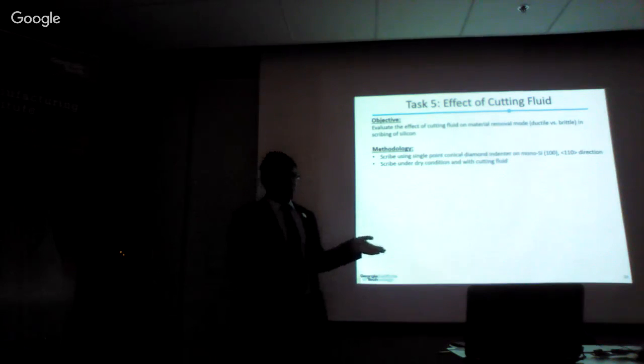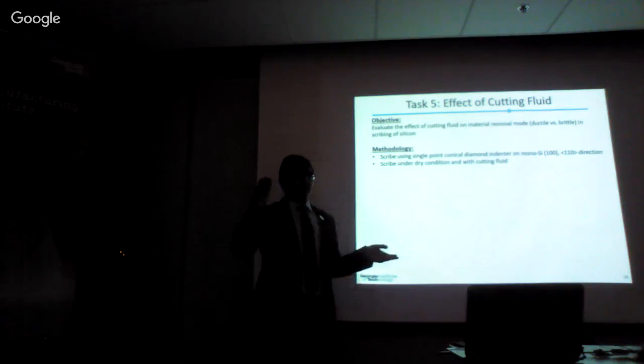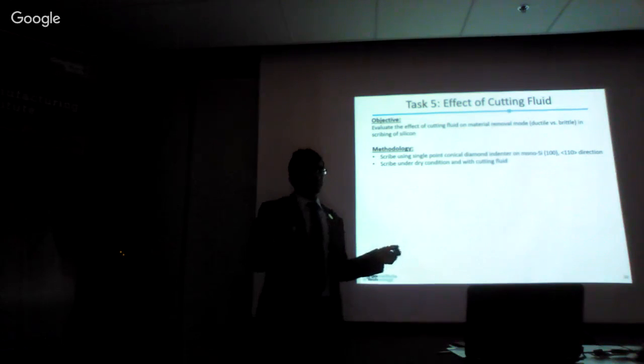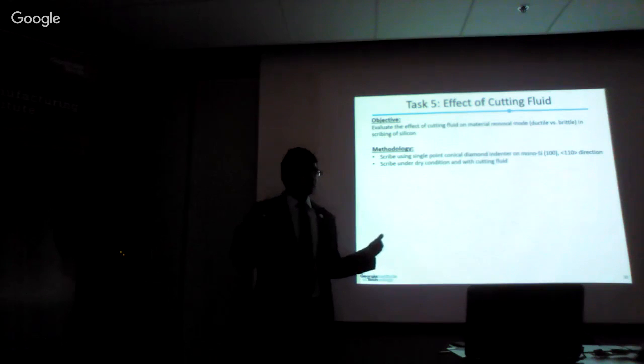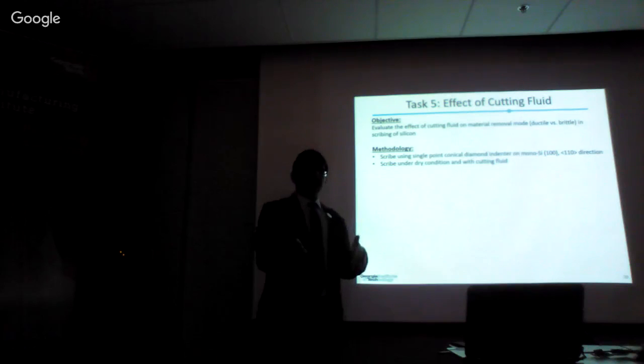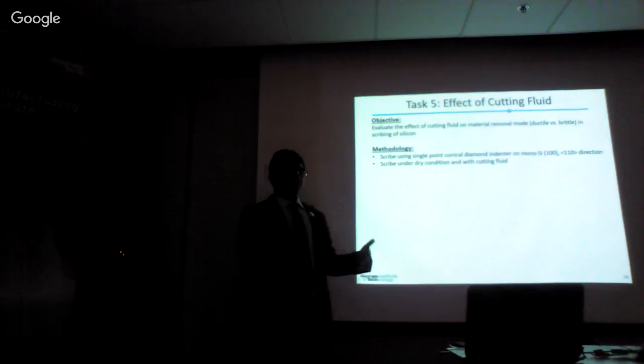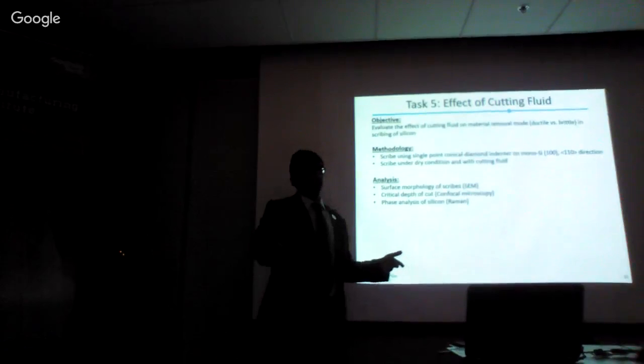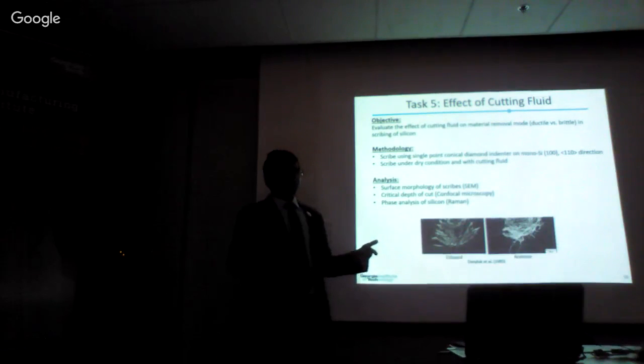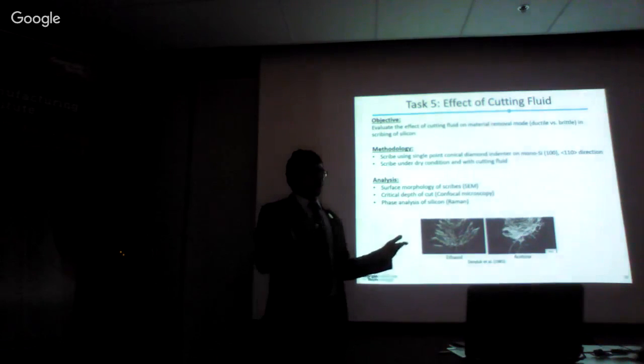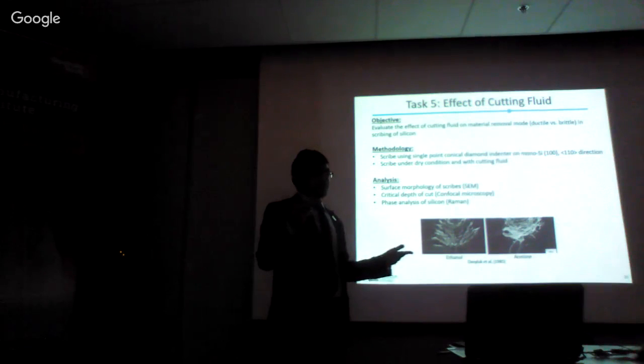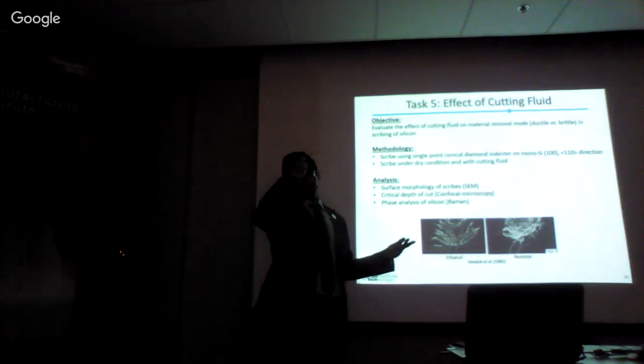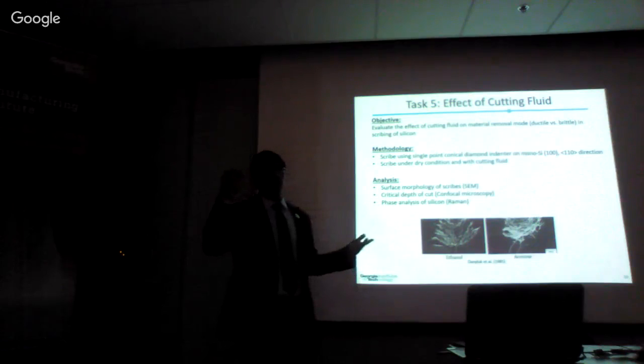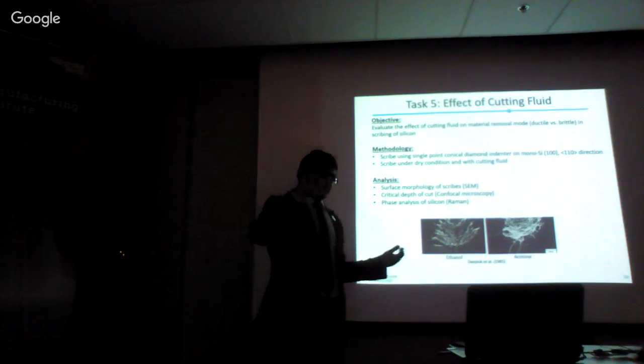To do this, we scribe, again using single point diamond tip indenters, on monocrystalline silicon of 100 orientation and 110 direction, and we scribe under dry condition and then using the cutting fluid. The cutting fluid was supplied to us by our industrial collaborator. We analyzed the surface morphology of the scribe. The confocal microscopy is used to find the critical depth of cut, and we also use Raman spectroscopy to find the phase of silicon after scribing.